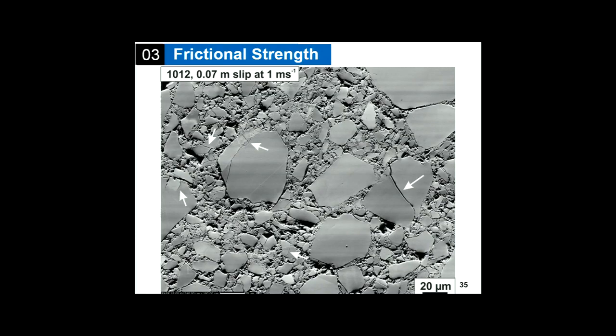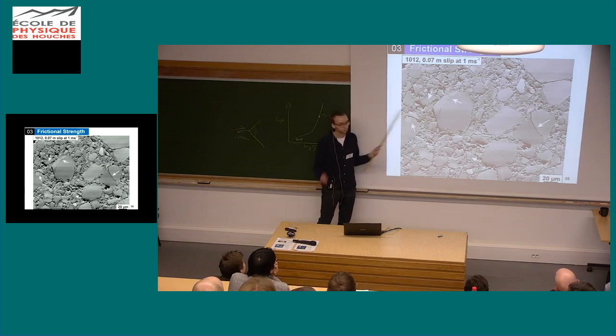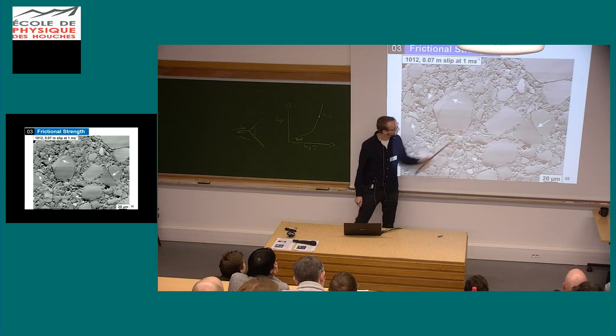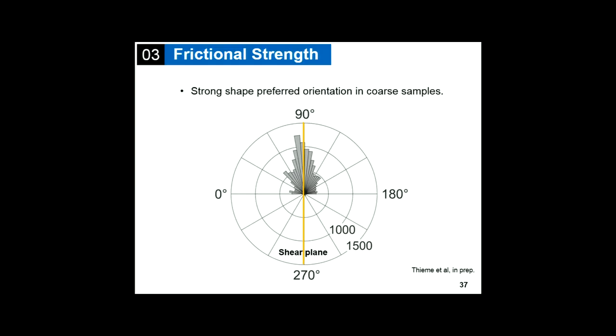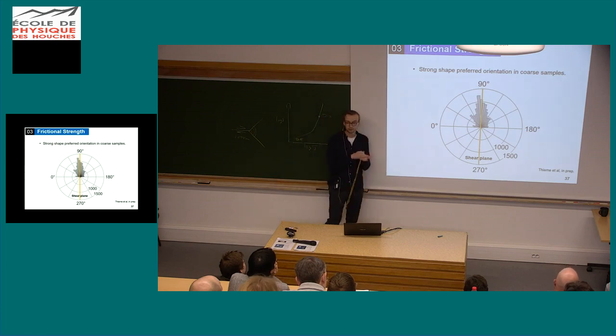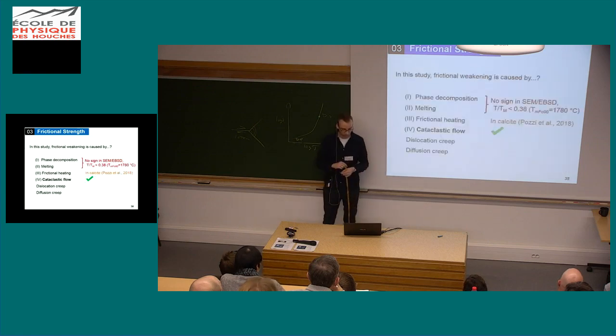Now, cataclastic flow. An SEM image of one of the samples with bigger grains shows that mostly all of the big grains are fractured towards the grain boundary. You have both fracturing and also the big grains surrounded by a matrix of really fine-grained olivine. Zooming in, the grains fracture from the outside going towards the inside and are surrounded by fine-grained matrix. Apart from that, we see formation of a strong SPO — the initial material starts without any SPO and very quickly develops a strong SPO with grains oriented parallel to the shear direction, which then gets reduced as deformation progresses.